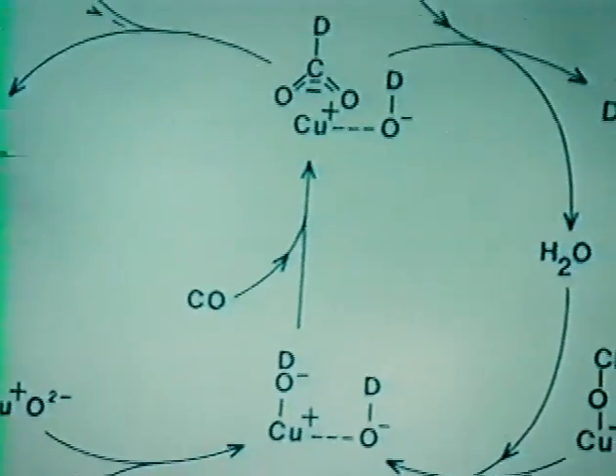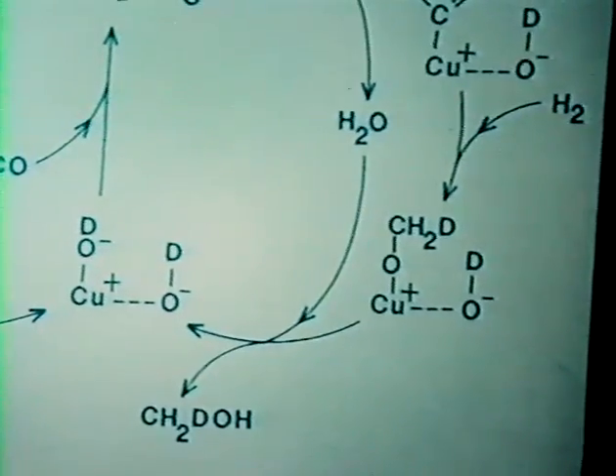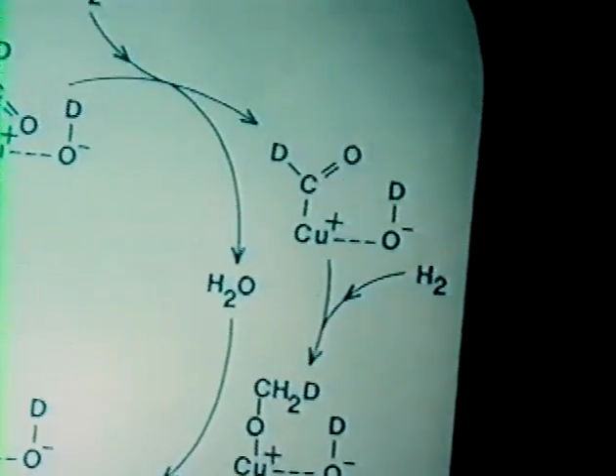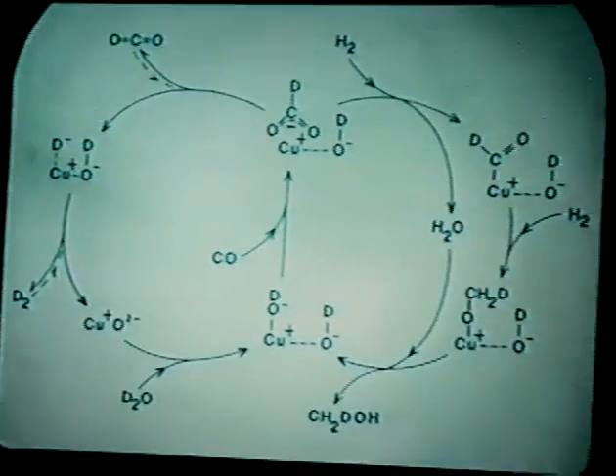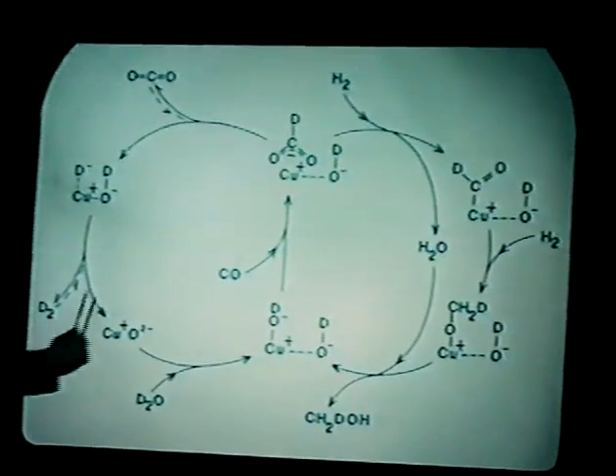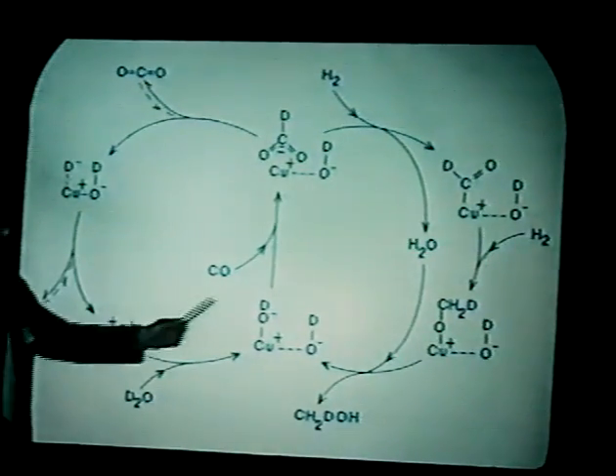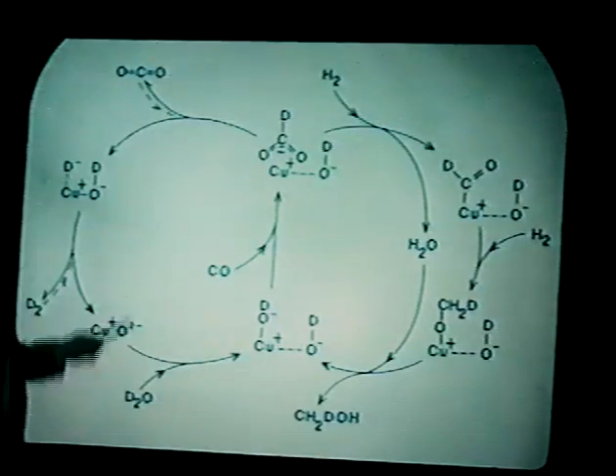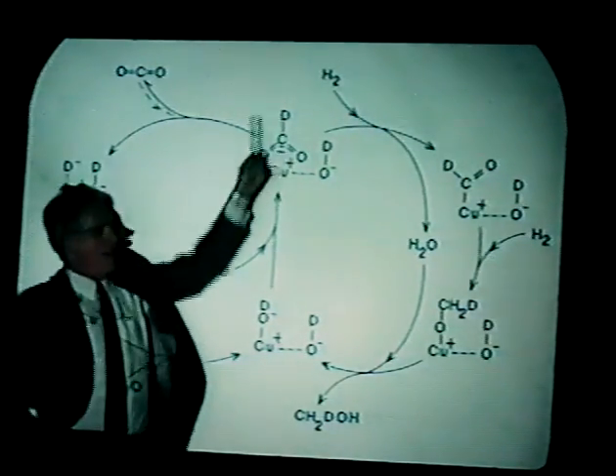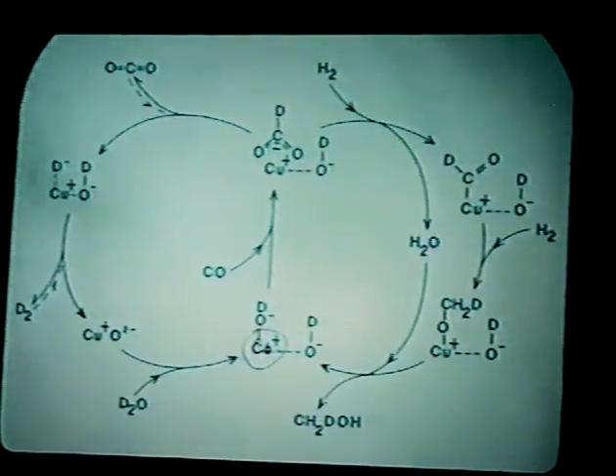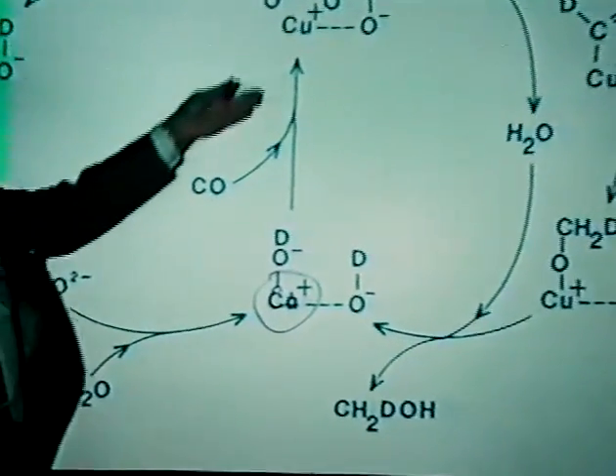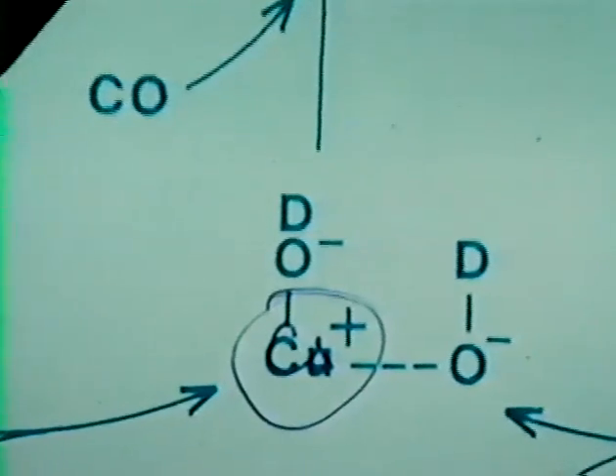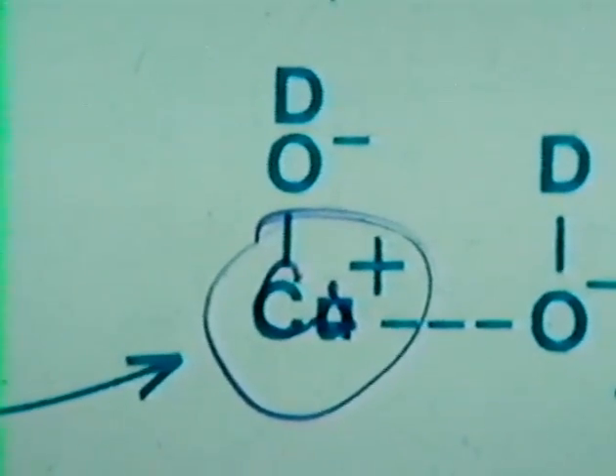And we suggested years ago in 1979 that the active center is copper 1+. There was a huge controversy in the literature, and we got tired of that controversy. And so we replaced the copper 1+ by an element which will do the same as copper 1+, namely to stick to an OH group, then insert carbon monoxide to make a formate ion. What occurs to you is to use an alkali metal, dope the catalyst on the surface by alkali hydroxide, let's say. Insertion of carbon monoxide into the OH bond to make formate is a readily occurring reaction. There's numerous proofs of that in solutions as well as in the surface literature.